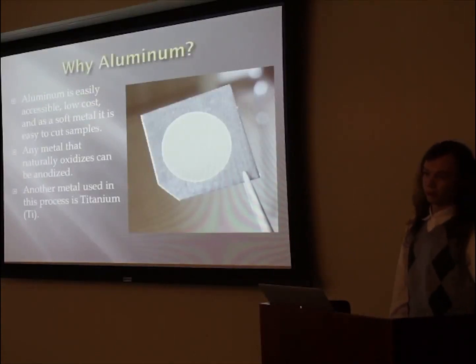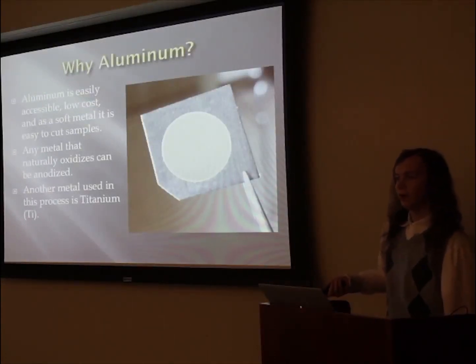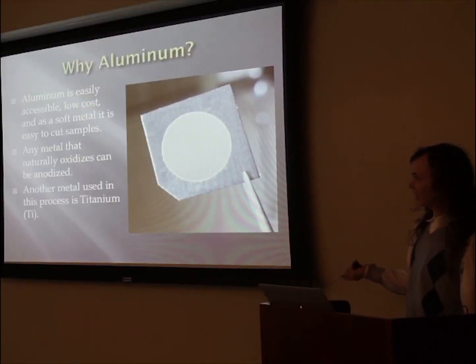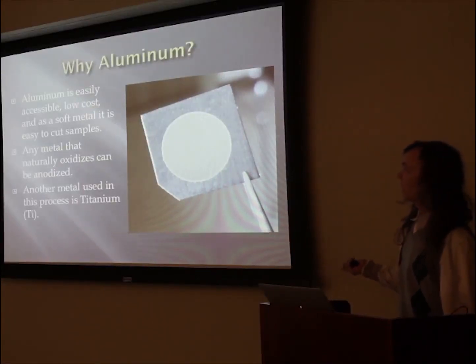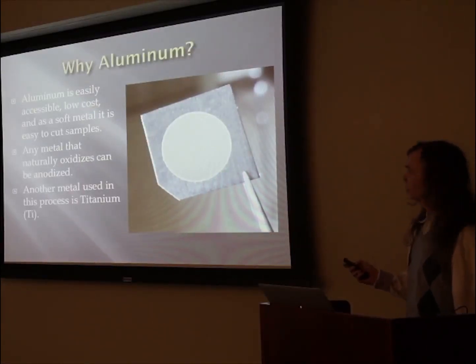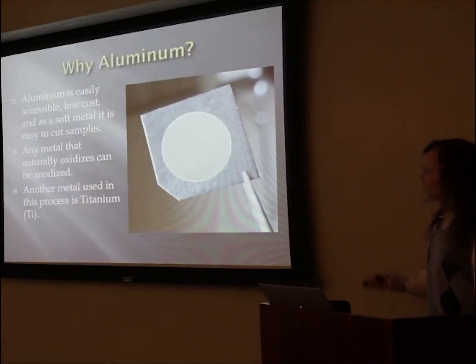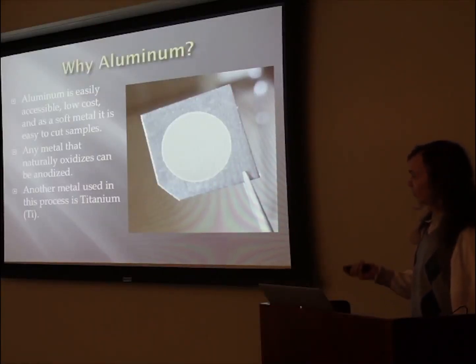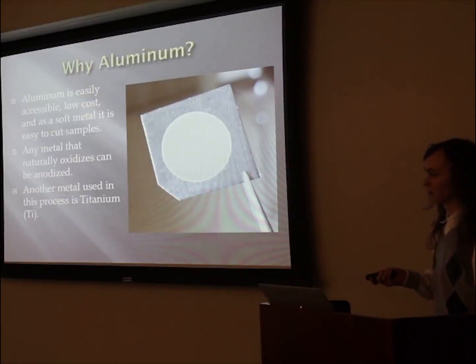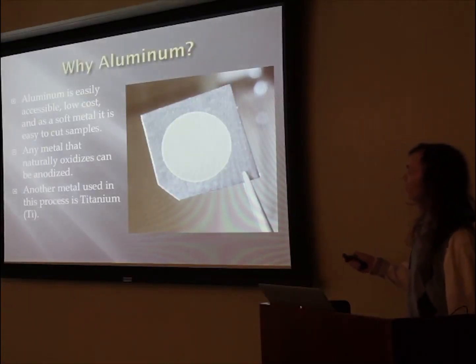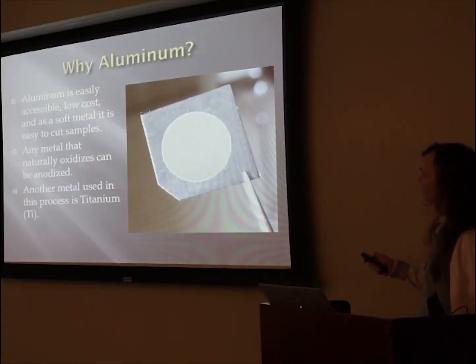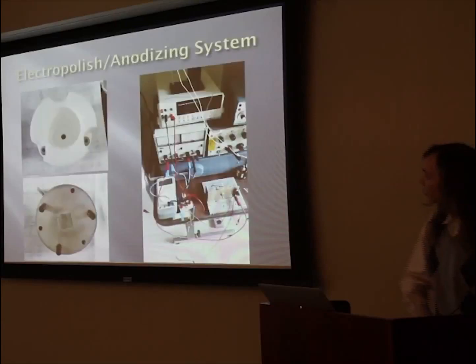So why do we use aluminum? Well, it's a soft metal, it's cheap, it's very easy to get in high purity, and it's easy to get samples from. So it makes it pretty ideal for making these kinds of samples. But it's not the only metal you can use. You can use something like possibly titanium. That's also used in other research that Dr. Shi does. So what you're seeing here is one of my samples. The outside edge over here being a hand-polished region of the aluminum, and the inside here is an electropolished region, which I'll talk about shortly.